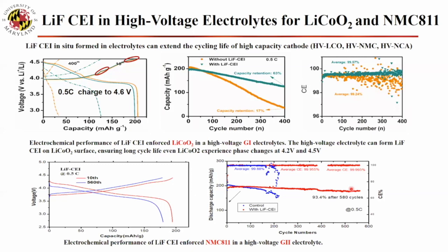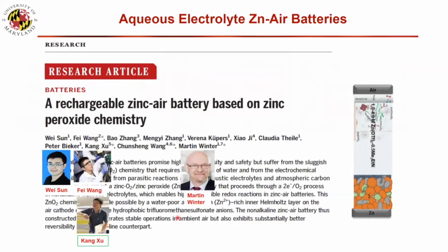So we show this is a concept, lithium fluoride, but this lithium fluoride should be formed in situ, not just pre-artificial, because if they have damage, they can self-heal. So that is organic. And then we talk about aqueous. In aqueous, we take an example of zinc air. So we want to emphasize in aqueous, if we put the ammonium OTF, they can form an SEI.